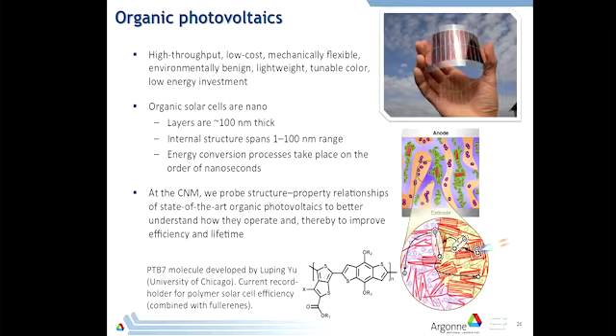And so here at the CNM, we've been working with a group at the University of Chicago who developed a molecule that currently has the highest record for polymer solar cell efficiency. And so we're working on organic photovoltaics, and that's basically solar cells that are based on organic materials because you can make them quickly, low cost, they're flexible, as is shown here. They're very benign to the environment, lightweight, all very good things. And these organic solar cells that we've been studying here are on the nanoscale. The layers that go into them are about 100 nanometers thick.